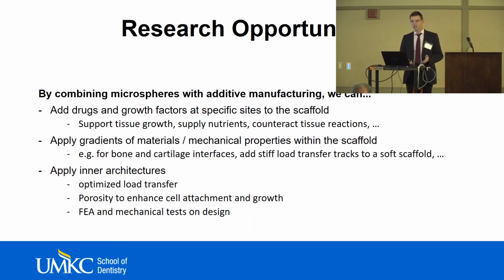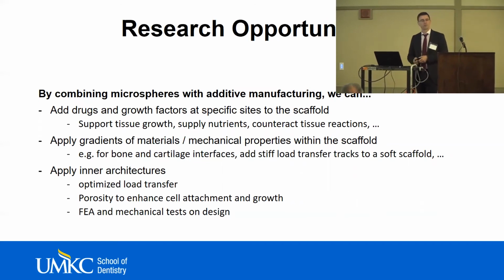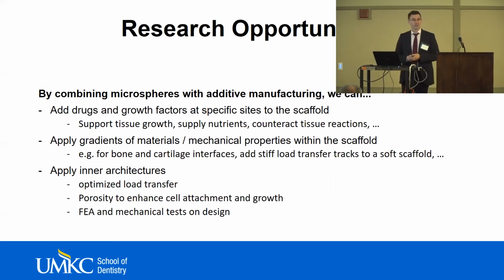We can also apply gradients of materials and mechanical properties within the scaffold, and we hope to create better scaffolds, for instance, in areas where you have bone tissue and cartilage tissue interfaces, so in joints. We can also add stiff load transfer tracks to a softer scaffold, where the softer material is actually necessary to enhance bone growth or tissue growth, while you still need to provide a track for the loads. And we can apply an architecture to optimize load transfers throughout the scaffold and play around with the porosity to enhance cell attachment and growth. So the possibilities seem endless, and I'm open to suggestions and collaborations with this.